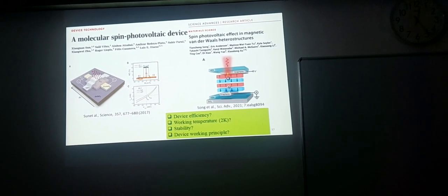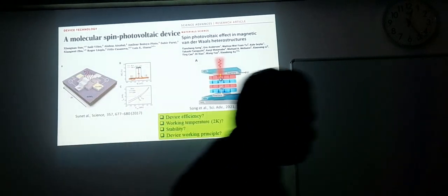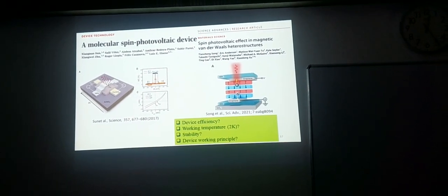This is a little bit different ideology than normal solar cells, because in solar cells we use sunlight and just collect the free charge carriers, electrons and holes, on both sides. But in this case it's a little different because they inject spin from a magnetic material into this material, and there are photoexcited carriers containing electrons with spin up and spin down. They try to understand how these spins interact with each other, and this leads to converting sunlight to electricity. This was the first paper that came out, but everything happened at 2 Kelvin, which is too low. It's quite hard to realize at room temperature.